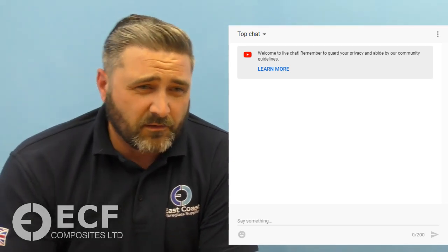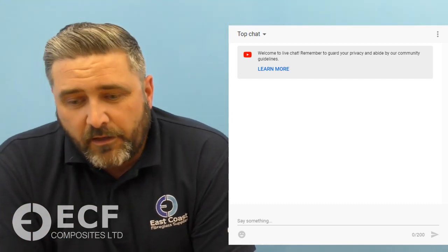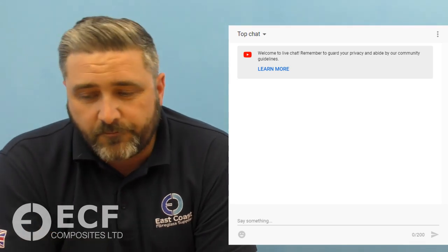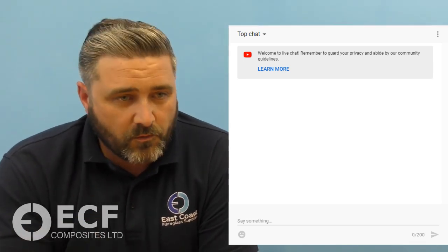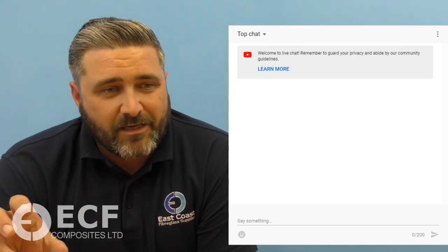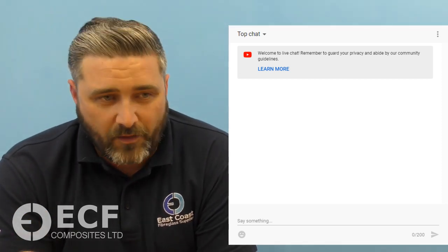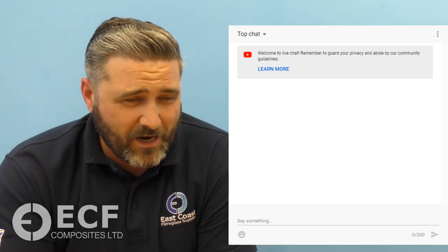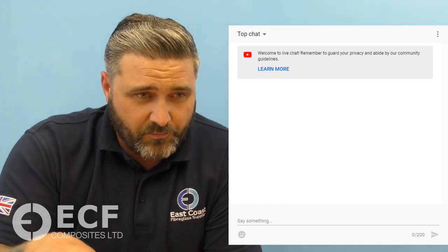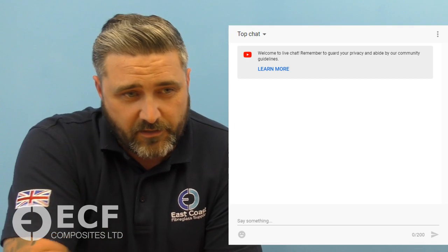Now, because of that tackiness, it doesn't really tend to go away until dust and dirt and grime lands on it. That's no good for a cosmetic finish. You don't want a tacky finish on a boat. So that's where flow coat comes into play. Flow coat is made from gel coat. It has 2% MW wax and styrene added to it, and that helps it cure without that tackiness. The job of the wax is to rise to the top surface as it cures, cutting off its exposure to the air, because the gel coat cure is air inhibited, so that's why you get the tackiness.